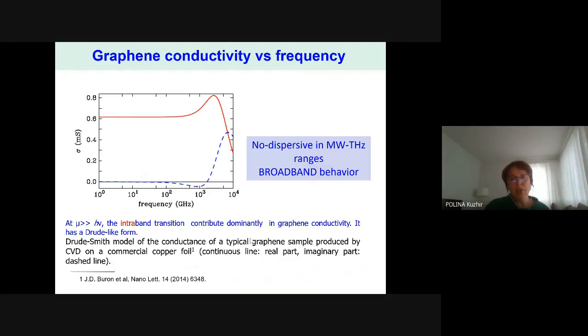Another important issue is that, in contrast to almost all other known materials, graphene is non-dispersive in the microwave and terahertz frequency range, because according to theoretical calculations, its conductivity, both imaginary and real part, does not change over a very wide frequency range, from 1 GHz to 2 terahertz. So we decided to try this graphene.